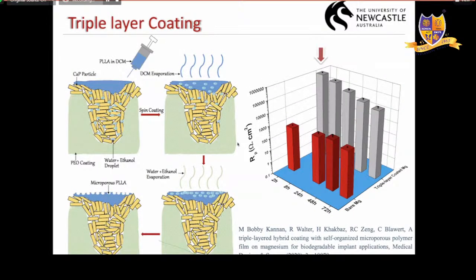And for the first time, we created a triple layer coating involving the porous structure, calcium phosphate deposition, and the polymer. This result is the highest resistance ever produced for this material, right? And we recently published it in Medical Devices and Sensors.